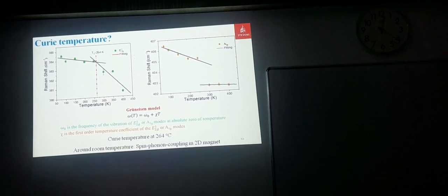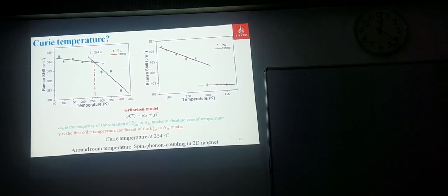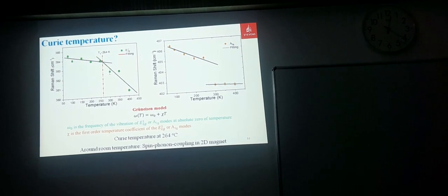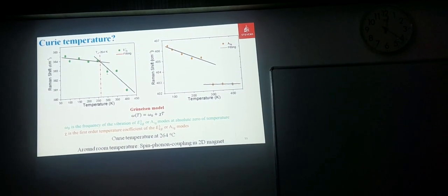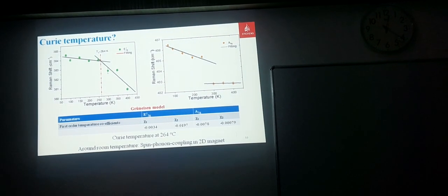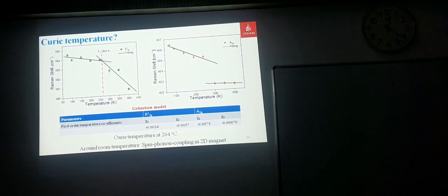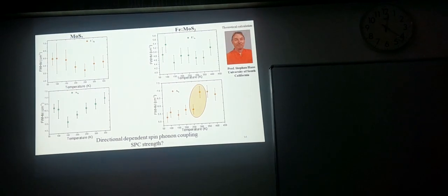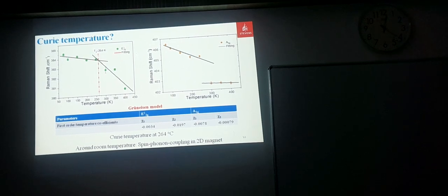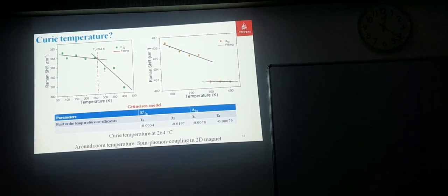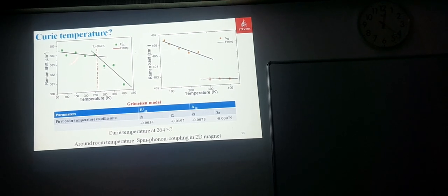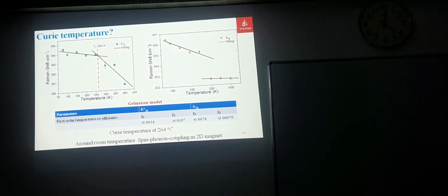Here you can see how the slope is changing in two different modes of vibration. When you talk about 2D materials, they have two different vibrational modes: one is the vertical, the out-of-plane, and one is the in-plane. So basically we understand how this in-plane and out-of-plane vibration mode changes over temperature. That is basically the phonon energy and phonon lifetime in this system. Here you can see two very different slopes compared to normal MoS2, and we tried to understand why this is happening. This is basically the Curie temperature. As I said, we already studied that the Curie temperature is close to room temperature. So we believe this is because of the phase change of this material at the Curie temperature.